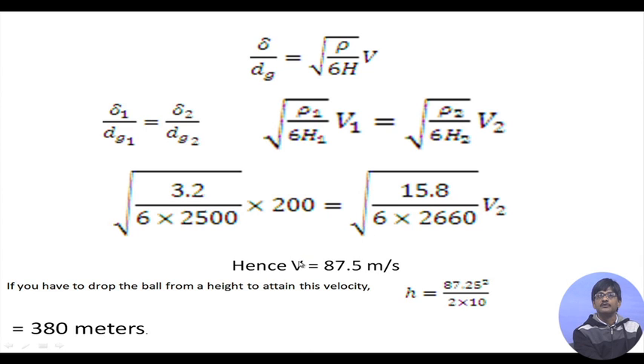If you drop this ball with a velocity of 87.5 meters per second on the experimental glass, in that case the delta by dg that we will obtain experimentally will be exactly equal to the delta by dg in the theoretical case, and that way in a scaled up experiment we will be able to estimate delta by dg. Last of all, if you drop it from a particular height, what should be this height? 380 meters. So, if you drop it from 380 meters, it will develop 87.5 meters per second.